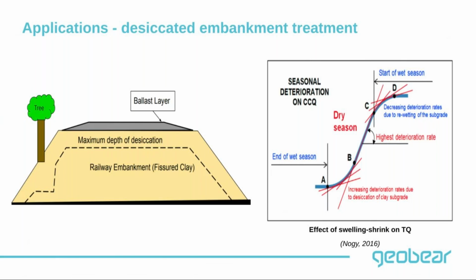As a result, what you tend to have is low track deterioration in the wet season. As we get into the dry season, the deterioration starts to accelerate, and it decelerates again as we get back to the wet season. So it's almost like a continuous shrink and swell cycle, and as a result, you will experience long-term deterioration. That's quite a common problem on our railways.